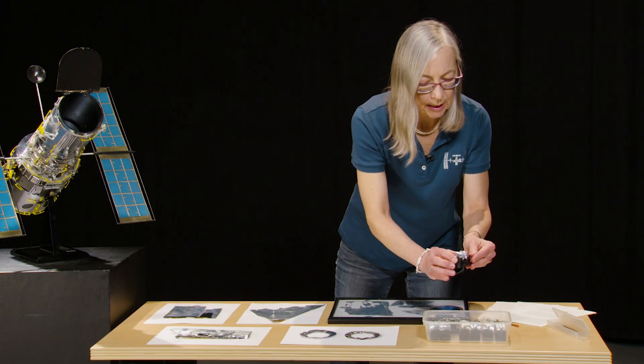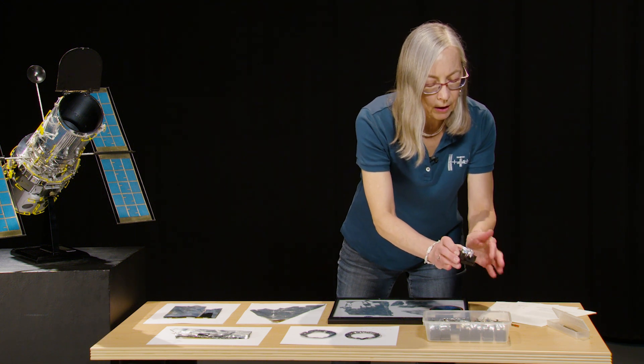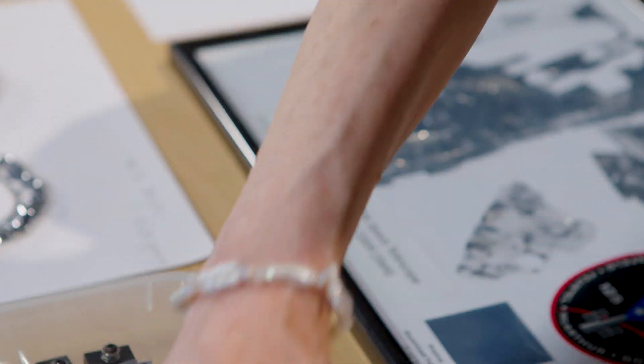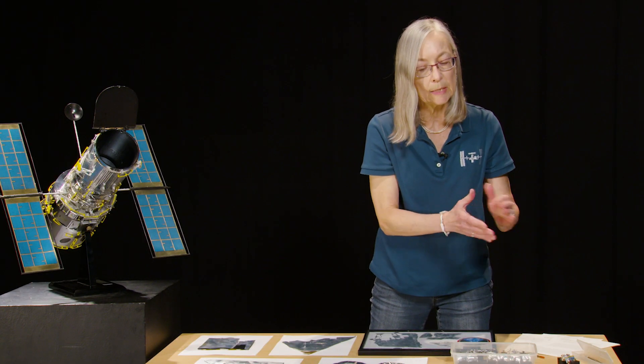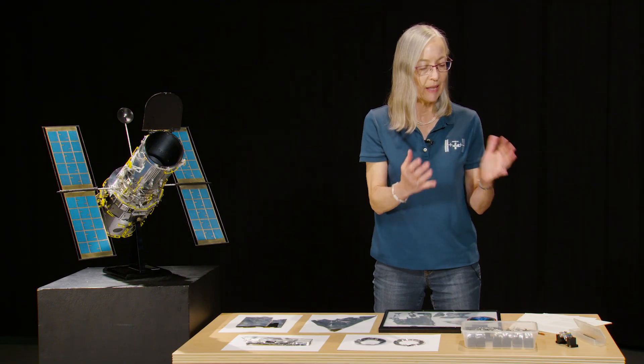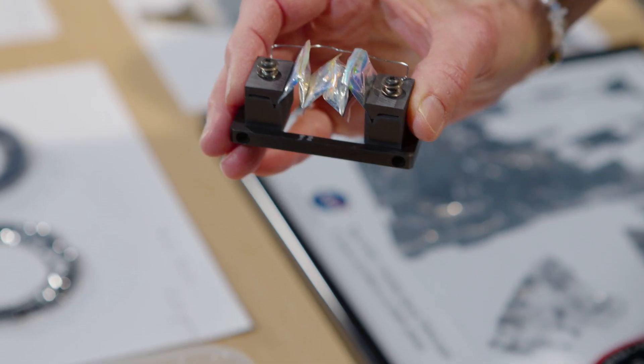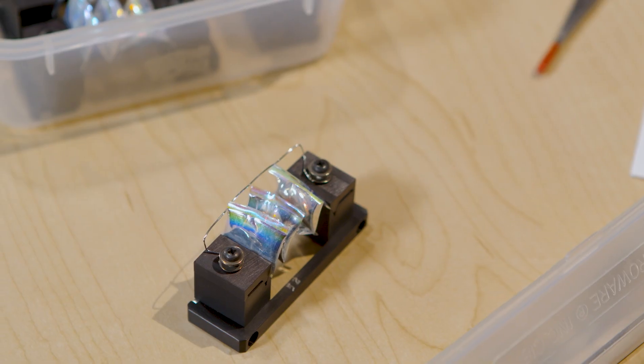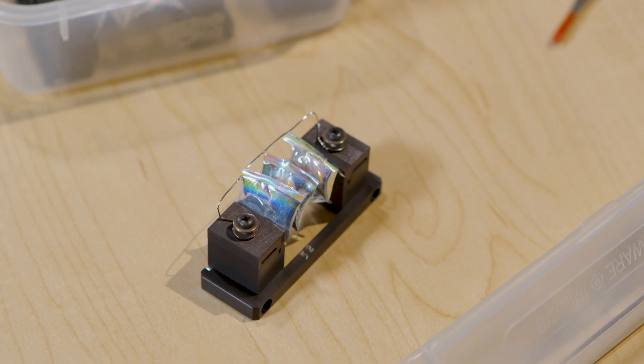These samples are the actual test samples. Some of them have a protective coating — this one has an iridescent kind of look to it. After they were exposed to the simulated space environment of atomic oxygen and UV radiation at Glenn, those sparkles ended up being the coating coming off of the material. The material is aluminized Teflon. That was obviously going to be a big problem if that happened up in space on the Hubble Telescope.